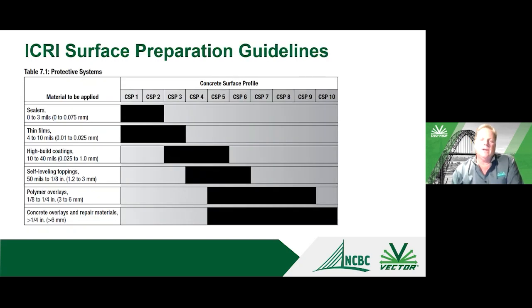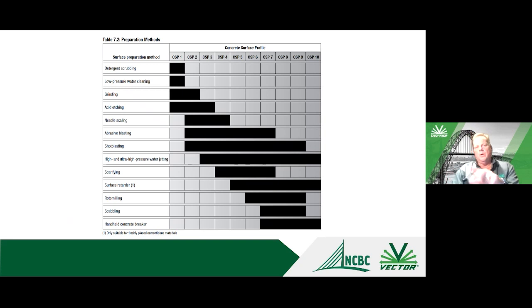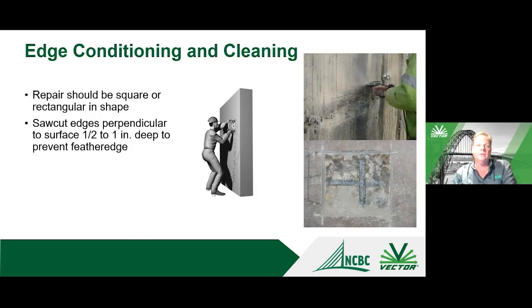These are just an indication of the concrete surface profile, that is the document that goes along with the chips, or the reference surface profile, and you see the different CSPs. And if you start looking into concrete repair materials, you're going to be going into CSP 5 or greater. And this is nice because it will give you what different types of techniques and tools can be used to achieve the desired surface profile. And then you can use the reference chips to compare to what you see in the field and see if you're getting the profile that you desire before the concrete repair is completed.